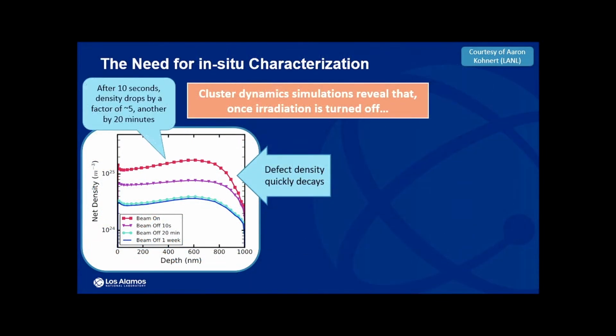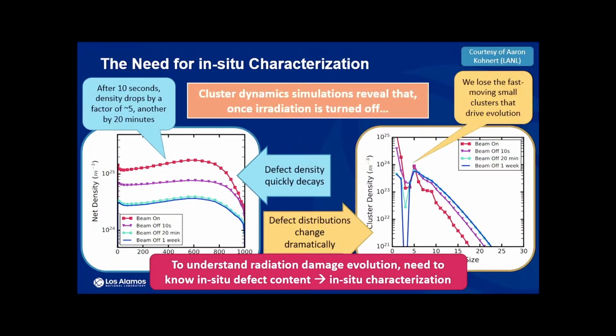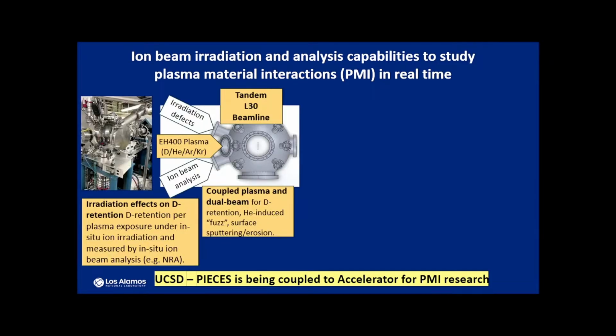This has actually been predicted by the cluster dynamics simulation, which reveals that even on the minutes, seconds time frame, those defects still change. And so we're in the process of setting up the coupled plasma onto the ion beam facility to look into the dynamics of this tritium retention process there.